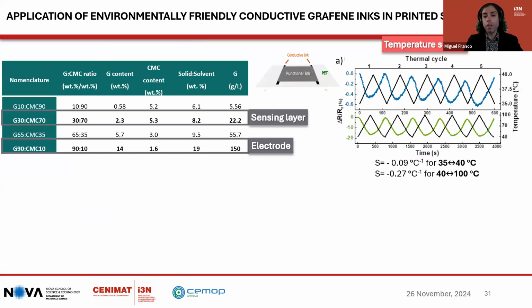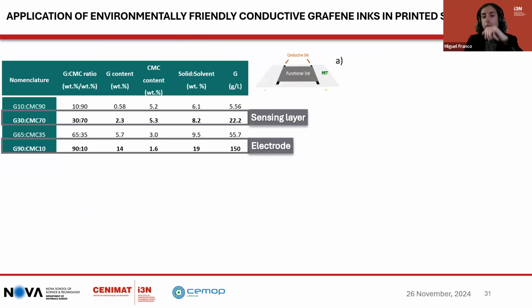Taking into account the percolation data, this formulation is interesting since it is close to the percolation threshold, to aim for higher sensitivity, while at a critical filler concentration, a rapid change in the electrical properties is observed when interconnected conductive filler networks are formed. The formulation with the highest graphene content was used as an electrode.